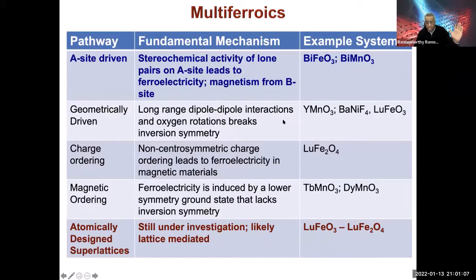And again, this is a quick summary. It wasn't meant to be extensive. There are many pathways. And indeed, one of the things that would be nice to have is other pathways to make new multiferroics. Now, you could have A-site driven multiferroics where the ferroelectricity comes from the A-site. A good example is bismuth ferrite, bismuth manganite. You could have geometrically driven multiferroics like yttrium manganite. Lutetium ferrite is a good example. In these cases, the polarization is typically the dependent order parameter. So these are called improper ferroelectrics, but they also have antiferromagnetism built into it.